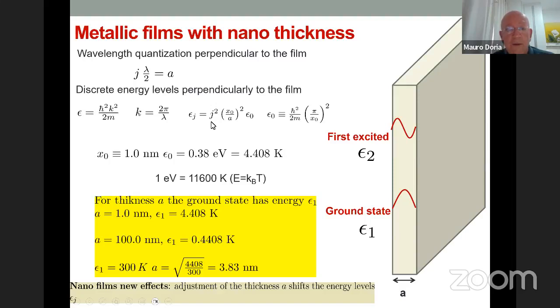So this is what I was telling you about: the quantum condition to observe this phenomenon is that you have to observe this discreteness. But if you take a going to infinity, to the bulk, this disappears. So you have to have the wavelength somehow limited by the geometry. They have to be similar. So you have to have j discrete numbers. So for instance, that's what's interesting. If you take x0 to be 1 nanometer, you compute this number here, and the energy level is 0.38 electron volts. So it's 4 Kelvin. So that's a connection, eV to Kelvin. So a equal to 1 nanometer, you have this energy here.